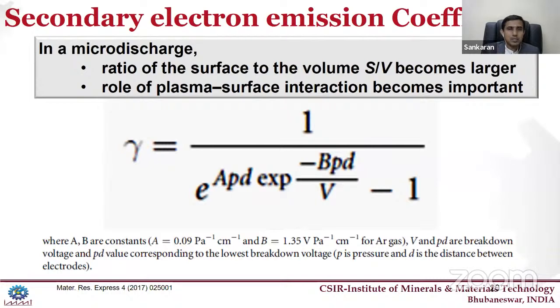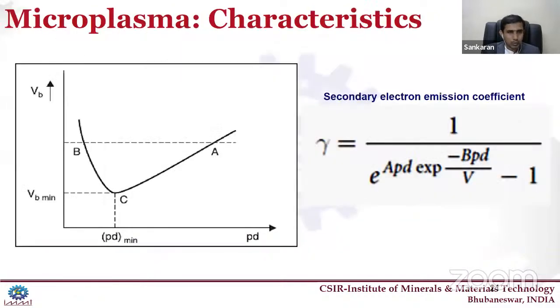Otherwise, the supply of secondary electrons is very low, so the plasma intensity will not glow more, and the device cannot withstand for a longer time. So we need a material with a very good secondary electron emission coefficient for getting a continuous plasma emission. We are working on that. The gamma, the secondary electron emission coefficient, is a very important parameter when working with microplasma. This is the Paschen curve I have explained before, and this is the breakdown voltage we are calculating.